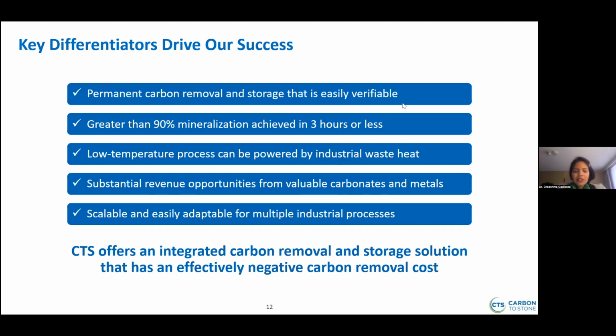And one of the key advantages is that because our process is engineered storage, it's easily verifiable. We're able to achieve high levels of mineralization in 3 hours or less. Our processes occur at temperatures below 80 degrees centigrade. Sometimes if it's calcium rich, it can actually occur at room temperature. If it's magnesium rich, then we have to go up to temperatures in the range of 50 to 75. But either way, it's much less heat intensive compared to some of the other DAC approaches that are available. There are substantial revenue opportunities, and we do have the opportunity to scale up with specific industry partners.